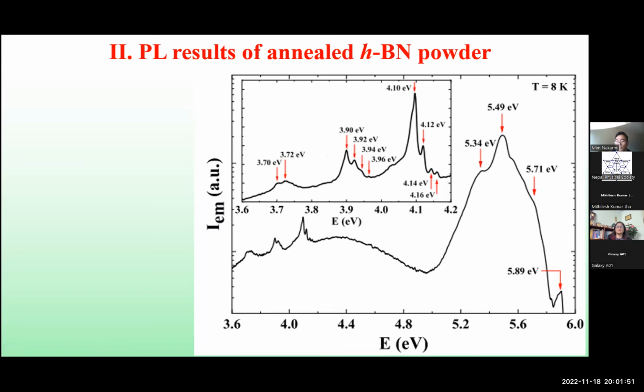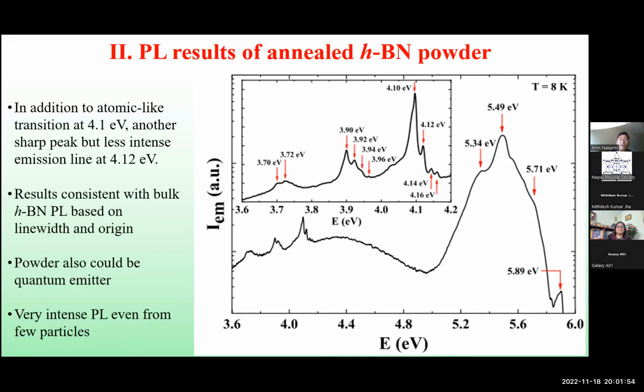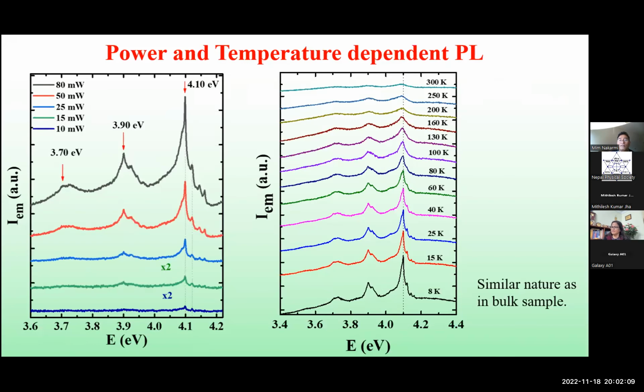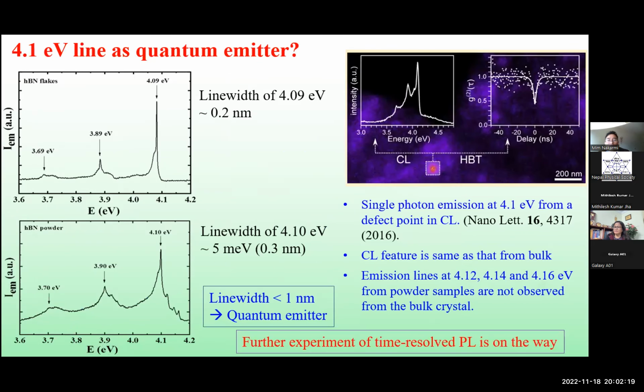So the conditions are the same. We also annealed the boron nitride powder sample. Crystalline quality of the powder, we cannot expect to be similar to the bulk. But the natures are the same. And same in the excitation power dependent and also temperature dependent measurements. So anyway, this is the most important summary of this photoluminescence result.